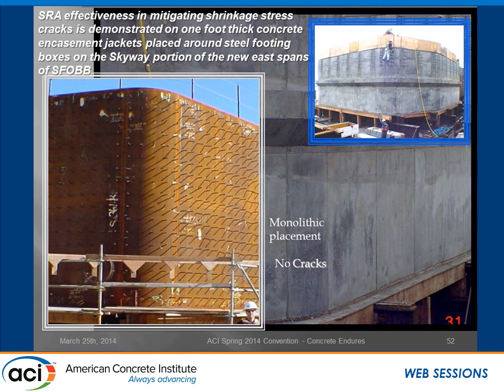How effective were SRAs in controlling shrinkage? Well, everybody out here, I'm sure, knows how hard it is to control shrinkage when you're trying to put a jacket around something. This is on the Skyway. Those are the steel footing boxes. And the steel footing boxes were poured with, I think it was a 1 foot thick concrete jacket. And the engineer out there had lots of experience with pouring jackets because it was Mark Woods, and they poured a lot of jackets on the West Approach during the seismic retrofit, and he used to call me up, and I had no idea how to control the cracks going around a jacket like that. And he knew the SRA was used in the segments to control shrinkage, so he just tried it there, and had pretty good results. And he also used it in the footings where he noticed there were radial cracks around stuff that protruded out. When we put the SRA in there, the radial cracks went away. So it was pretty effective there.